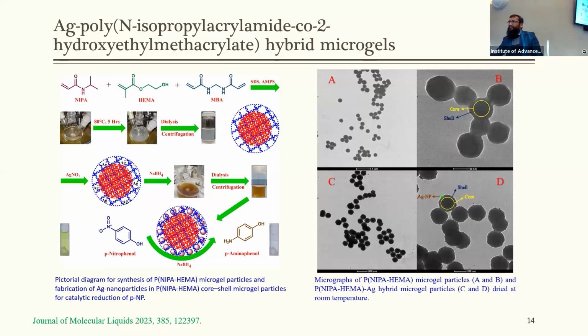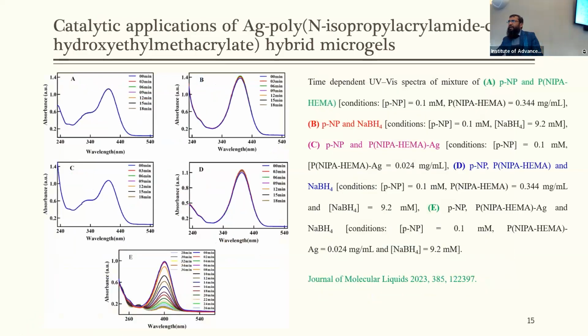The microgel system was characterized by transmission electron microscopy, and the A and B images are associated with the pure microgel system, while the C and D images are associated with the hybrid microgel system. We can see the silver nanoparticles were successfully loaded in the outer region of the microgel system. The resulting microgel system was used as a catalyst for reduction of 4-nitrophenol into 4-aminophenol.